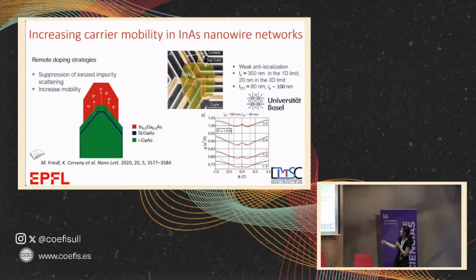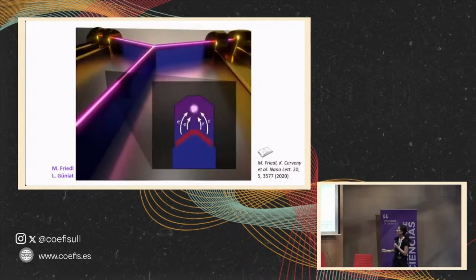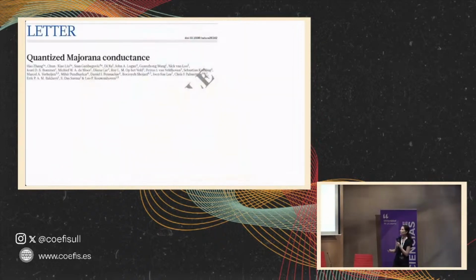You can see here that the mean free path is 300 nanometers or 20 nanometers, depending on how we model the curve. And the spin-orbit length is 80 nanometers, which is the length that you need to change the orientation of the spin. So it means that we can start to have a handle on the orientation of the spin with an electric field. So this was good. And so the dream was that now we would have these 1D wires that we would couple to superconductors and create these Majorana fermions. But then something happened.